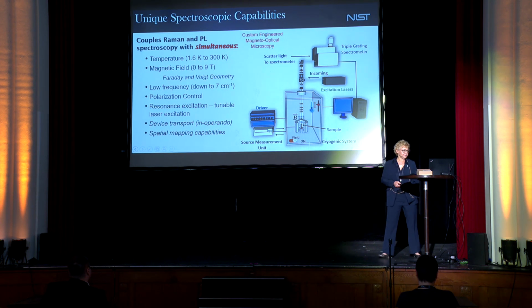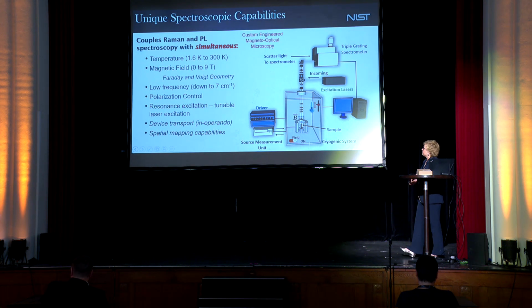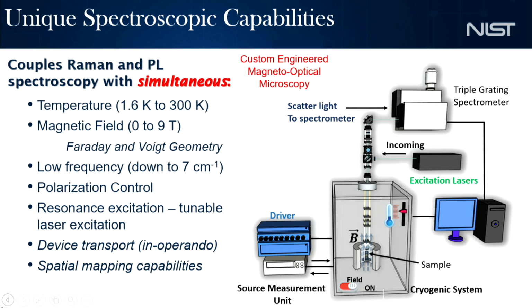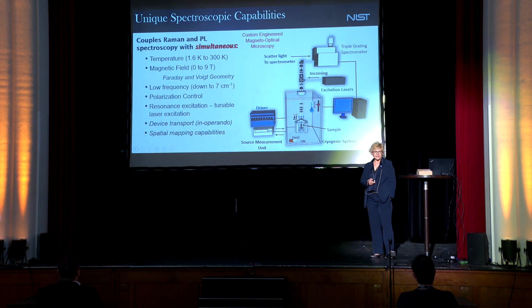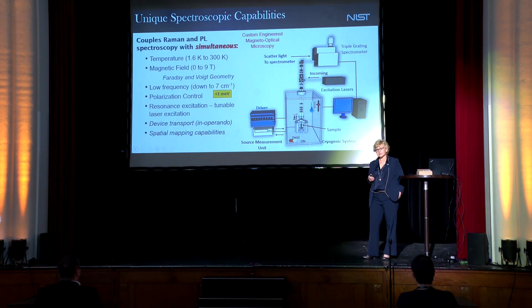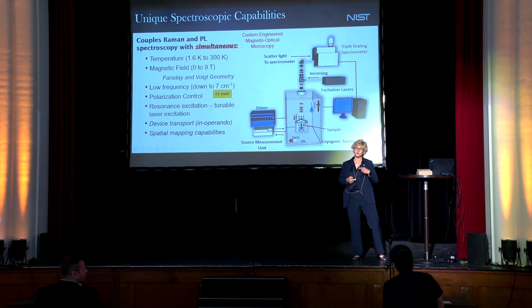Okay, this is the larger capability. We've coupled a triple grating spectrometer. For those of you doing Raman, often you're using a single grating spectrometer, because Raman has a very poor cross-section and you don't want to throw away the light three times. But in fact, that's what we do. That allows us to get very low in frequency space, on the order of about 7 wave numbers, which is 1 meV. That is important often for 2D materials, like we've heard before. Some of the modes between the layers are really in that low frequency window.